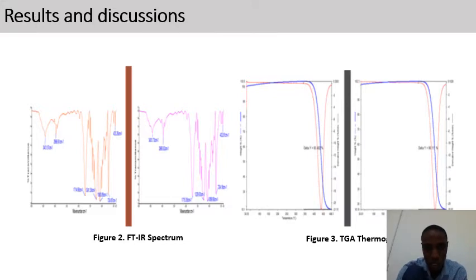On the FTIR, there is no effect of gamma irradiation on the functional group of the PET before and after irradiation. As you can observe from the plot, we have the same wave band for both regular and irradiated PET, but on the thermal analysis using the TGA, we observe some differences.